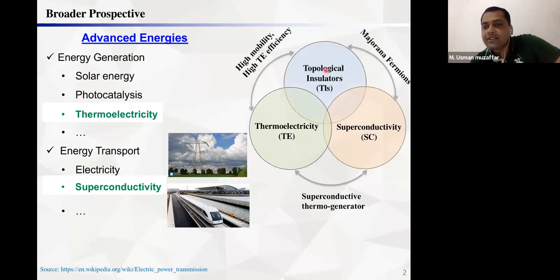There is another physical phenomenon known as topological insulators. We know that these materials have high carrier mobility. In the bulk they act as insulators, and on the surface they have a zero gapless surface state, just because of the backscattering-free surface states. That's why they have high carrier mobility. So if we connect these two, so that we can exploit the high mobility in thermoelectricity, then we can get high efficiency.